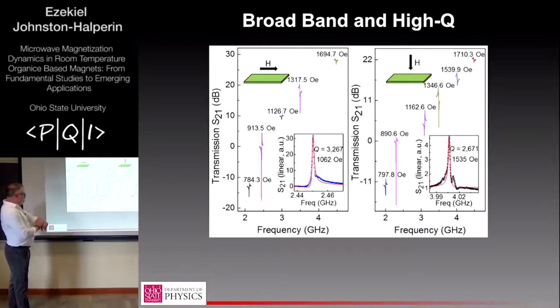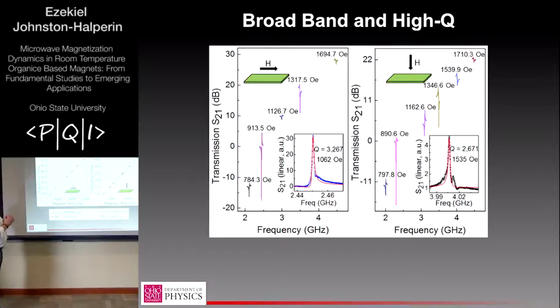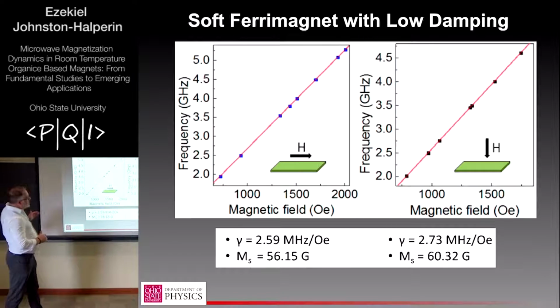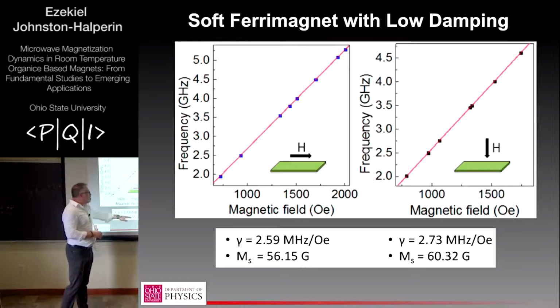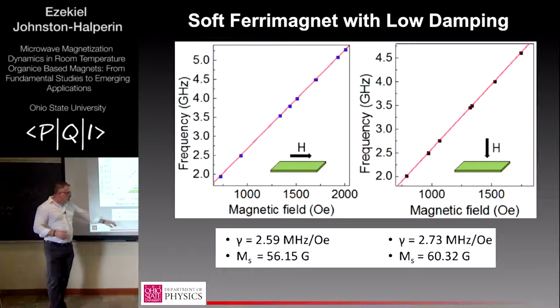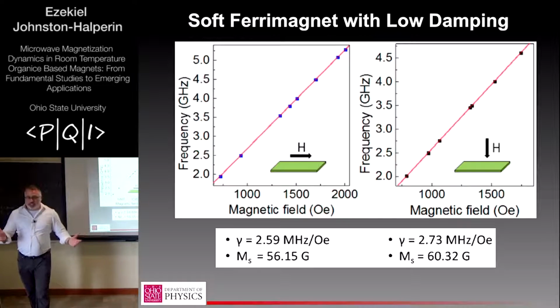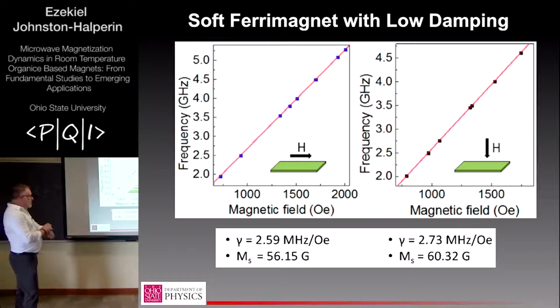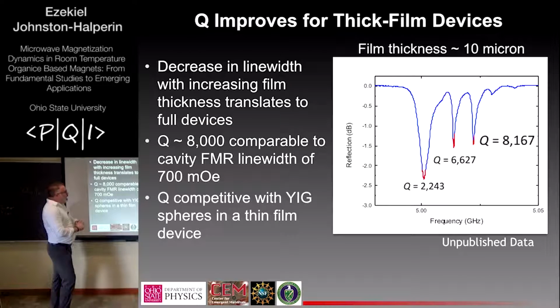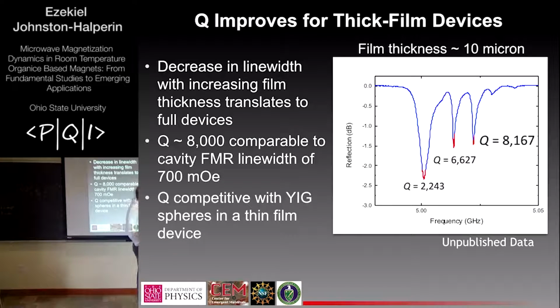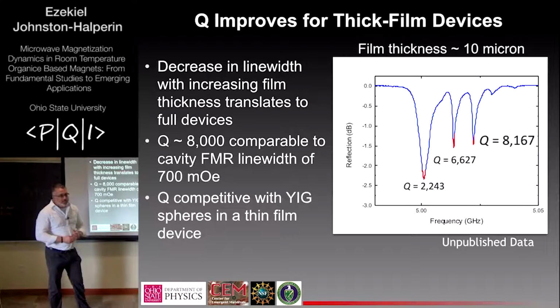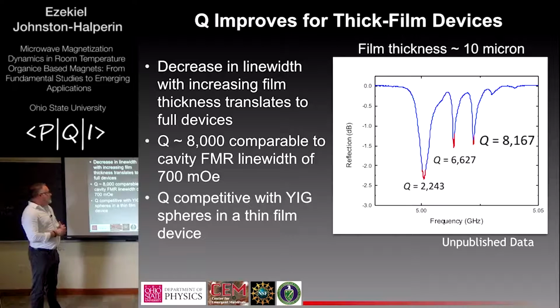And yeah, I'll show you the thicker films in a second. Because it's broadband, we can track and extract the gyromagnetic ratio and saturation magnetization. This matches what we see in DC and cavity FMR reasonably well, and is comparable to the 700 millioersted line width I showed earlier. Now you can start to see for a thick film, so this is now a 10 micron film, that we're seeing very distinct peaks, very clear spin wave resonances coming out of the broadband FMR.